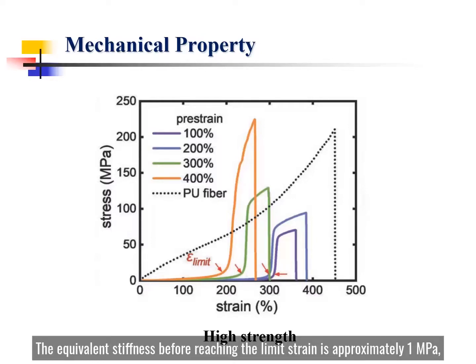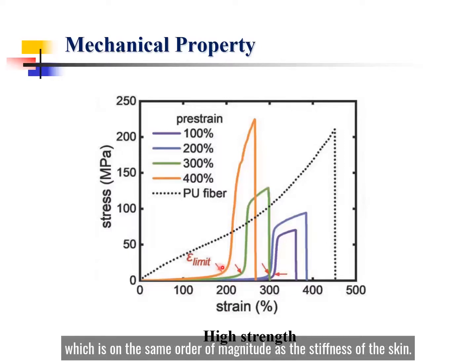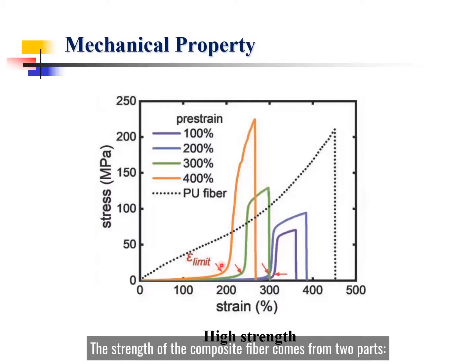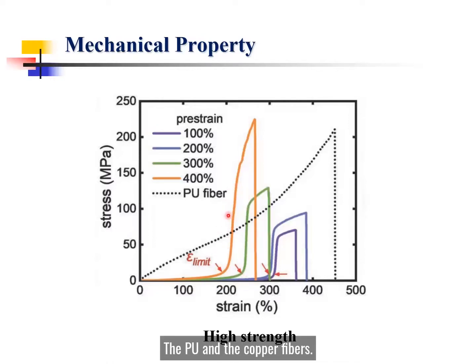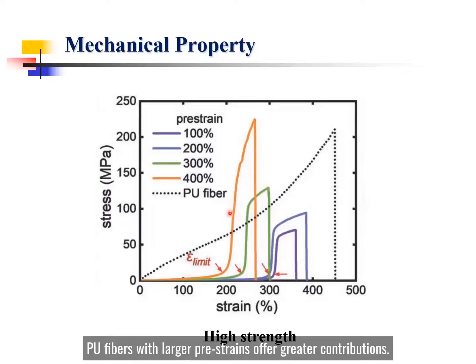The equivalent stiffness before reaching the limit strain is approximately 1 megapascal, which is on the same order of magnitude as the stiffness of the skin. The strength of the composite fibers comes from two parts, the PU and the copper fibers. PU fibers with larger pre-strains offer greater contributions. Thus, the strength of the fibers is greater at higher pre-strain.